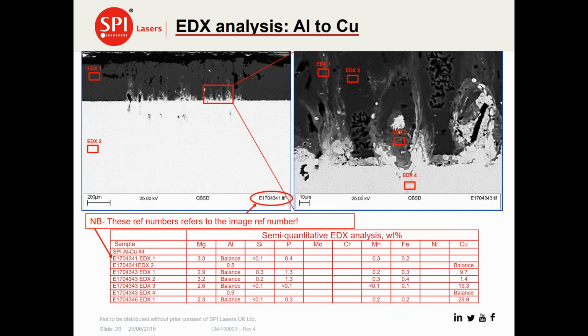Just looking at this in a little bit more detail, this is an SEM image, and subsequent EDX analysis of a section join. This is again looking at aluminium to copper. What this is basically showing is that although we do have a mixing of the metals itself, you're almost stirring metal up rather than metallurgically bonding them into an alloy, into an intermetallic zone here. There are no alloys formed, therefore it's overcoming some of the challenges associated with traditional laser welding.